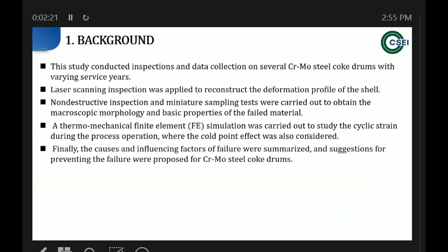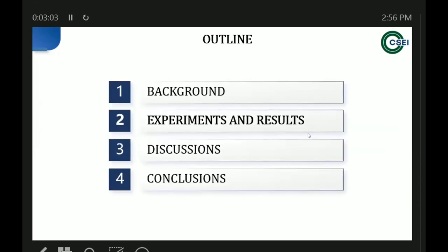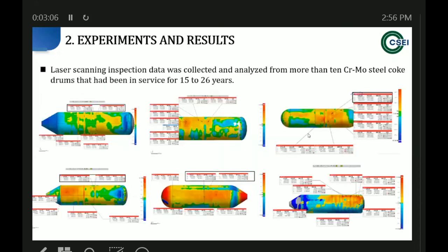This study conducted the inspection and data collection of several chromium molybdenum steel coke drums. We used laser scanning inspection to construct the deformation profile, and we also used miniature sampling tests to obtain the properties of the material. We also used finite element simulation to obtain the strain and the stress during this process, and we concluded the reason for the failure and also give some suggestions to prevent the failure problem. The next part is the experiments and the results.